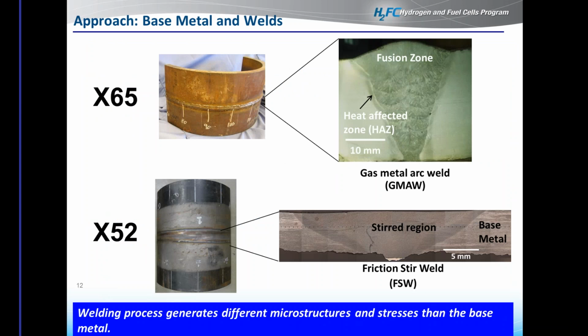So the two pipelines we looked at are X65, which is girth welded, and it was produced using a gas metal arc weld. Gas metal arc weld is a MIG welding process in which the weld is built up through consumables, and it's a multi-pass weld. You can see that the microstructure of the fusion zone is distinctly different than, let's say, the base metal. And you can actually see kind of this halo region around the weld where you have the heat affected zone.